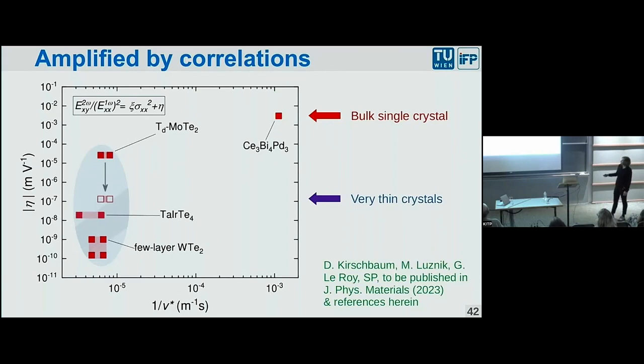and the relevant quantity that is really related to the Berry curvature is these points here. There's some uncertainty, and these points, in fact, belong here, according to the authors. So the effect is very small, and it could be detected in these systems because they are all essentially very, very thin. And then you can put very large fields on them. Okay, so with few layer thickness of these materials, you can in fact detect the effect. But the effect in our system is not at all thin. It's just a bulk material. We put very small electric field. It's much, much, much larger.